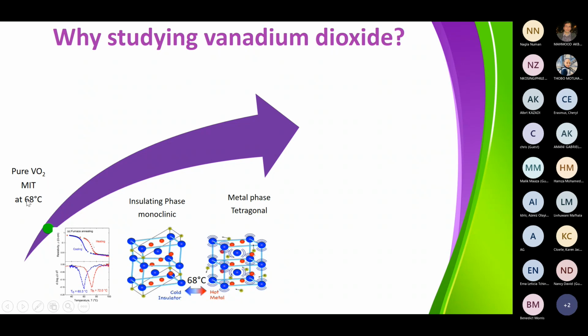The transition is occurring at about 68 degrees Celsius, and it is accompanied by a change in the structure, because in the insulating phase you have a monoclinic structure, and when you go into the metallic phase, it goes into a tetragonal phase. So it's basically a change in the structure, which is also accompanied by a change in the electronic properties of the material.